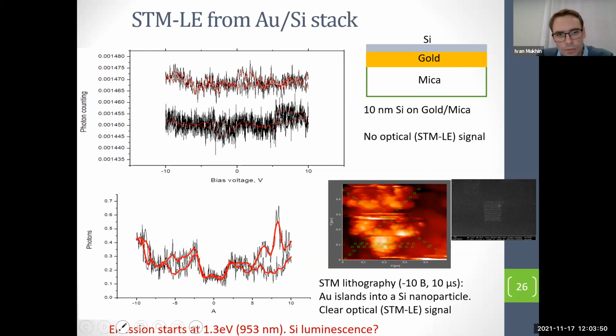And this value corresponds to the quantum efficiency of the silicon photodiodes used. So we believe that we can emit light in the infrared spectral range. It means that we can excite optical states in silicon, because we don't have any such spectra in gold. This light emission corresponds to silicon. We need to study it in detail, but the main idea is that in the hybrid alloy of gold and silicon, due to an inelastic tunneling process, we excite optical modes due to plasmon properties.